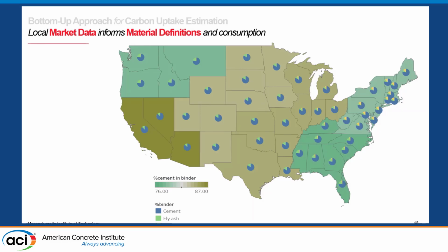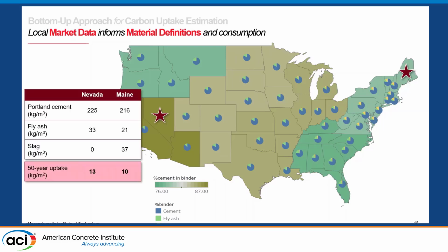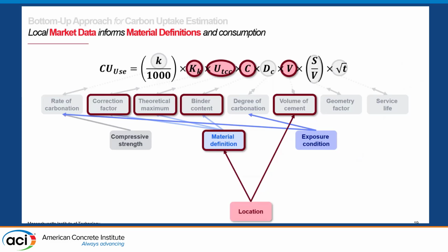And the material definition includes information, for instance, about the binder content, both the amount of binder and the percentage of cement that's found within the binder. The different colors on the states represent the percent of cement in the binder, and the pie charts represent the composition of cement, fly ash, and slag within a typical concrete mix for these regions. And if we take two states that have different amounts of binder, but more specifically a different composition of the binder, we see that Nevada, the state with the typically higher amount of Portland cement per meter cube of concrete, leads to a higher 50-year uptake value. So information about the material definition definitely affects the magnitude of carbon uptake potential.